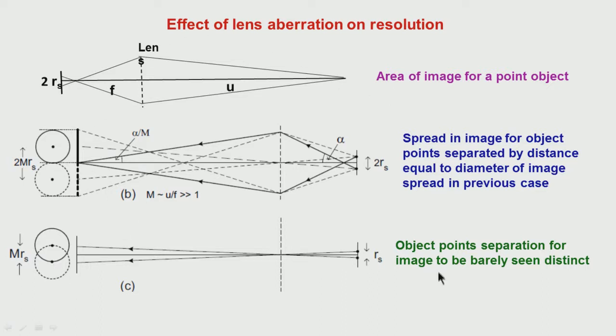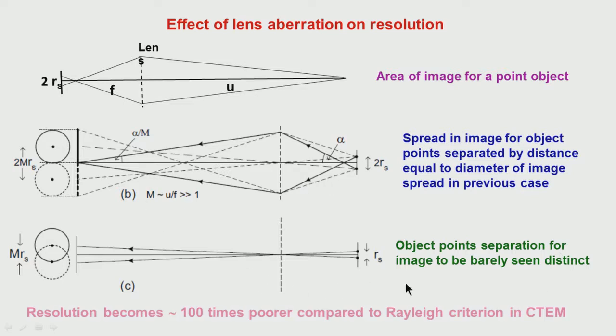Here we have considered only the spherical aberration, because that's one of the most important. In fact, as we go, we will see that this makes the resolution 100 times worse compared to what the Rayleigh criterion dictates.